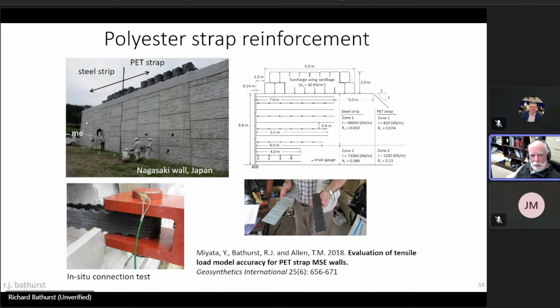And the only difference was on one side they used steel strips, and on the other side they used PET strap. And you can see the two reinforcement materials that I'm speaking about here. A comparison of those two walls allowed the influence of the stiffness of the reinforcement to be isolated. This other picture that you see here is a test on a sacrificial piece of PET strap reinforcement to test the connection and also the interaction or stress transfer between these PET strap reinforcements and the fill.